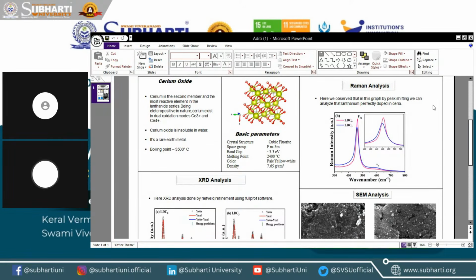Raman analysis: here we observe that by peak shifting in this graph, we can analyze that lanthanum perfectly doped into ceria and enhanced some physical and chemical properties of cerium oxide.